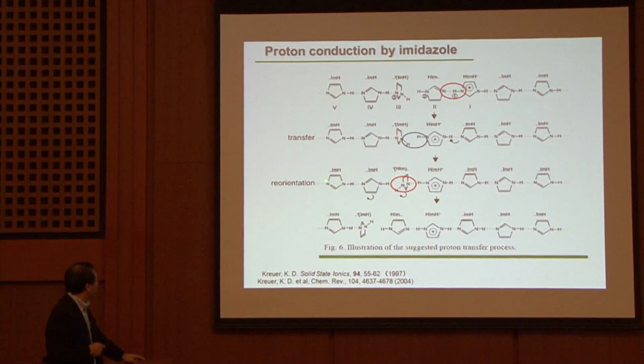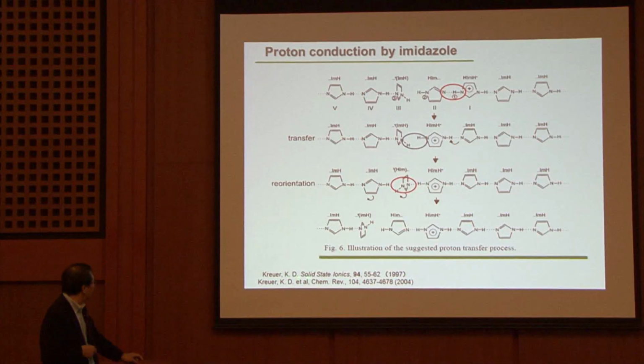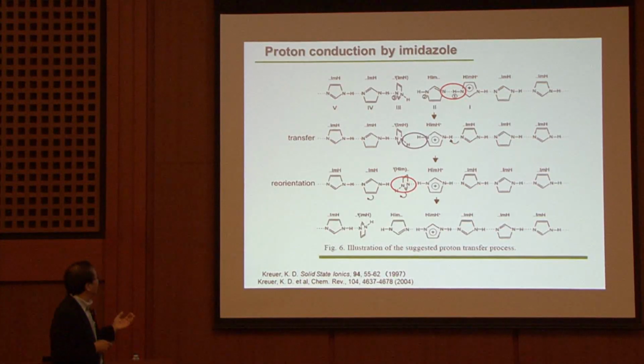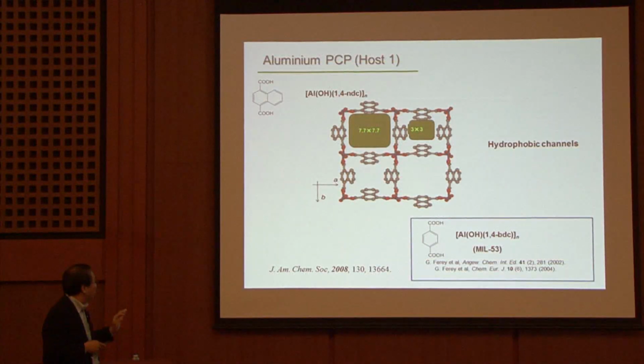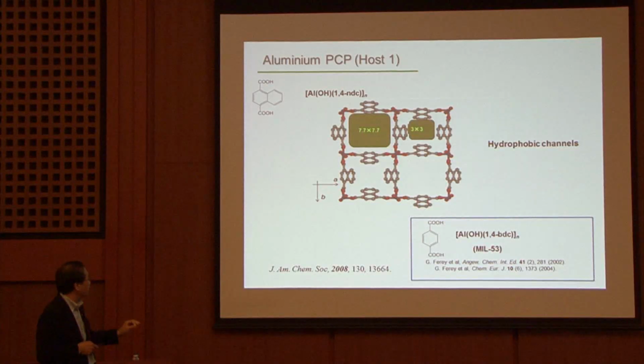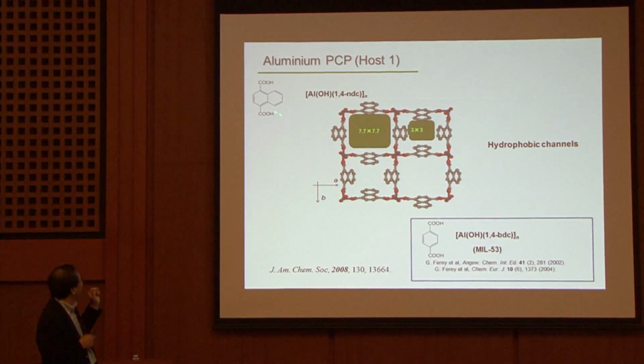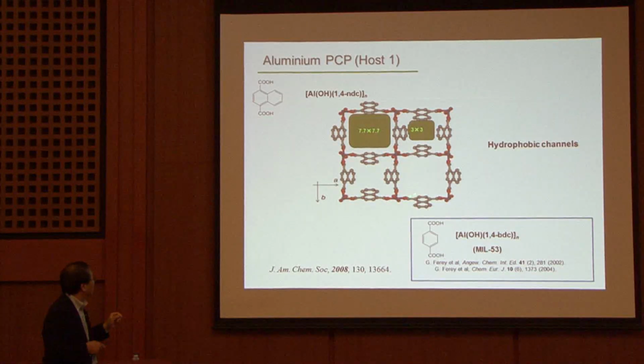Of course, this idea was already found in 1997 and before. So we want to use this kind of proton conduction by imidazole through the Grotthuss mechanism. In order to do this, we have to synthesize a new type of framework. Gérard Férey synthesized very famous materials, MIL-53, by using aluminum and benzene dicarboxylate. But instead of this, we use naphthalene dicarboxylate. So we determined this crystal structure.